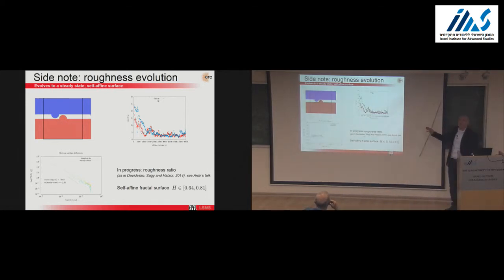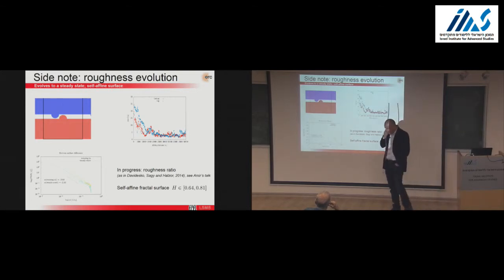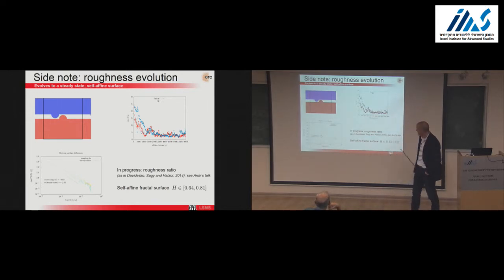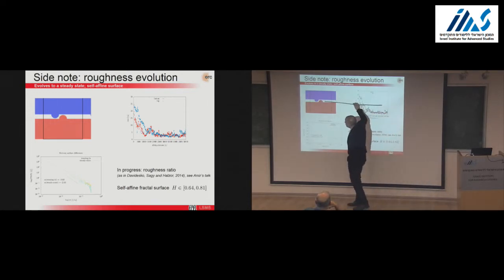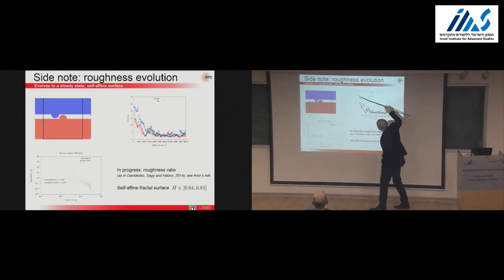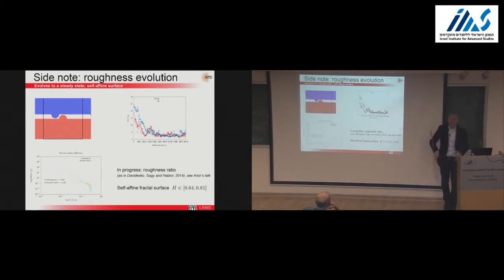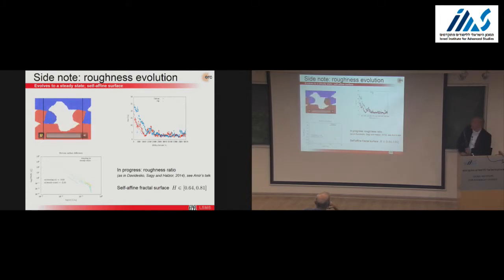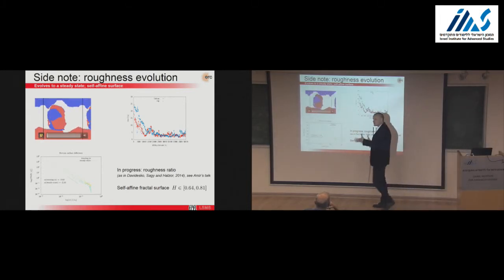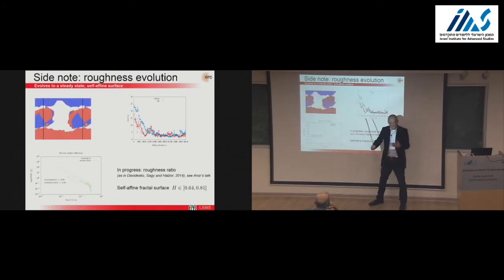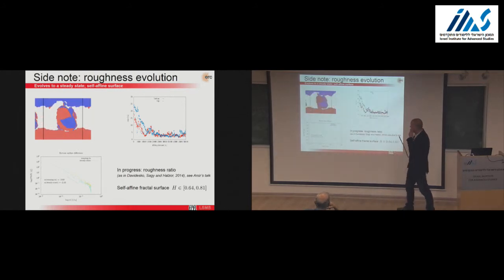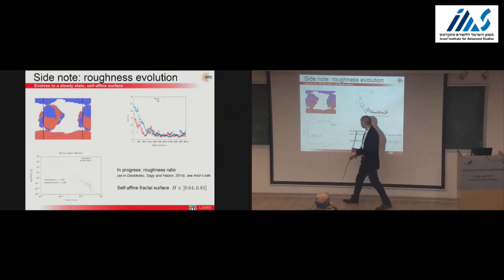So this is very preliminary. I want to highlight one slide from a PhD student, Enrico, whose goal is to understand the evolution of surface roughness. So initially, you start from very flat surfaces. There's going to be this collision. You're going to have large cracks, and you're going to form a large RMS roughness. But then there will be a running-in process, but it takes a very, very long time to see this running-in process emerge. And you have to develop techniques to extract the surface automatically. You don't want to do it by hand all the time. So you see this running-in process.